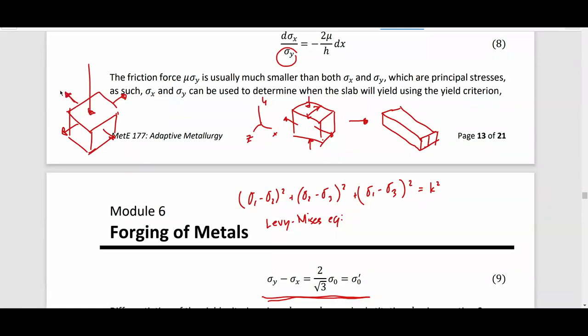to. So kunwari gusto ko plane strain siya dito, only moving in this direction and this direction, and not in the z direction. So kunwari ayaw ko mag-move siya dito. So the way you do it is kailangan may stress ka na ina-apply dito, tama? Para kina-counteract mo. Okay? So it means that for you to have plane strain conditions, you need actually three stresses, no? So meron pa ring stresses on the y, and on x, which are resultant stresses because of the motion of your material, kumbaga yung material mo kasi nagpo-flow papunta diyan, thereby producing residual x direction stresses, no? Pero yung sa z, dapat meron ka ring residual z direction na stress pag ganyan.